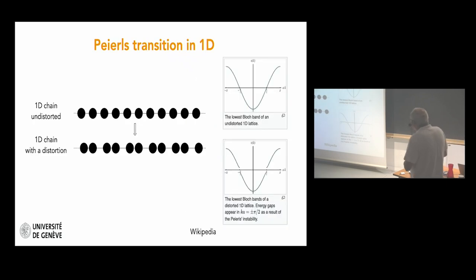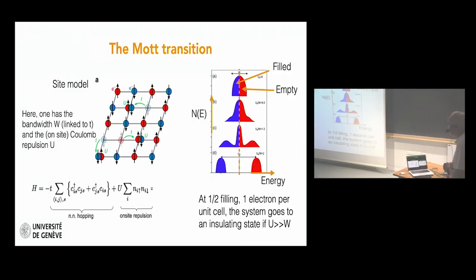And it was mentioned that, for instance, in 1D, if you have a 1D chain with 1 electron per site, you have a half-filled system, but we know that in 1D you have the Peierls instability, and the lattice goes through a distortion, forms dimers, and then you double the unit cell. By doubling the unit cell, you now open a gap at the previously half-filled band, and your system is turning into an insulating state. Was also mentioned, I think several times, the Mott transition. It will be important here.